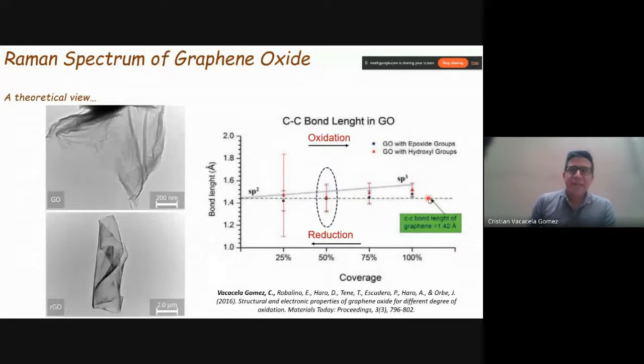But in real life, or at least in our oxidation methods, we can reach a maximum of just 50%. But what is the idea? We introduce the oxygen functional groups to exfoliate our graphite by the chemical route in order to get graphene. Now, if I want to recover the properties of our graphene materials, or the pristine graphene, we need to apply a reduction process.